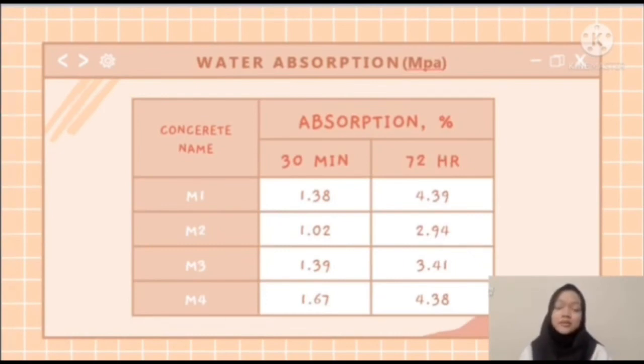Next test is water absorption. So this is the table of results from the water absorption test. Water absorption is to comprehend the concrete's relative porosity and permeable void space. Two 150 mm cubes were used to conduct absorption and permeability voids testing. Saturated surface dry specimens were stored in a 105 degrees Celsius hot air oven until they reached a constant weight. After removing the item from the oven, it was allowed to cool to room temperature.